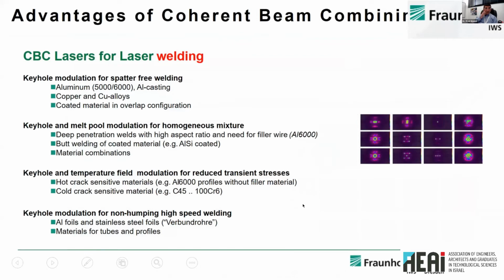So to summarize these advantages, we're talking about the ability to do keyhole modulation for spatter-free welding. We can do a melt pool modulation to get a homogeneous mixture. We can do a temperature modulation to reduce the transient stresses, and keyhole modulation for non-humping high-speed welding.